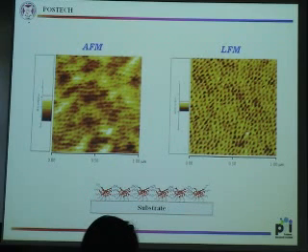We think that in a selective solvent of PVP, that is ethanol, the surface could probably be covered by the PVP. But when the film was dried, the lower surface energy block, PS, wanted to find the air interface. That could be possible. By pushing the PVP block to the side, the PS could then be exposed to the air. Definitely we need more study to verify this kind of core-corona inversion and the structure before and after the ethanol treatment.